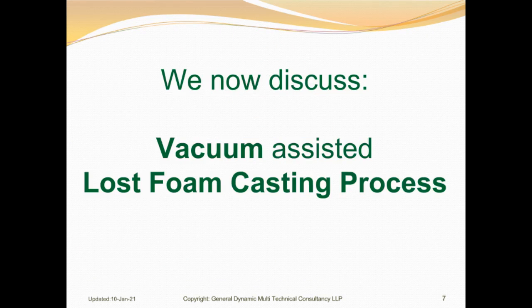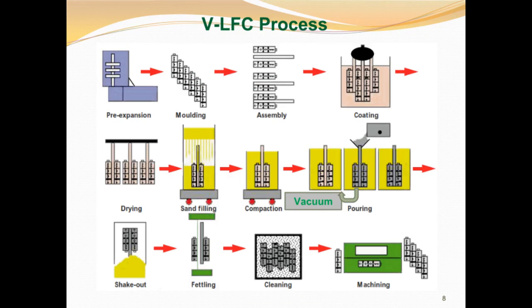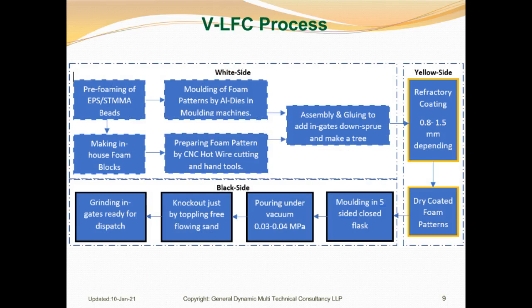Now let us discuss the vacuum assisted lost foam casting process, step-by-step. With 1 kg of EPS we can make 300 kg castings, so in fact pattern cost would be just about 50 paisa in the casting cost. That's still amazing to many of us. Firstly, we have to make foam patterns. Either EPS beads are pre-expanded and foam patterns formed by a molding machine inside an aluminum-shaped die, or we take EPS thermocol blocks and cut them to the shapes needed by hot wire CNC or a manual foam block cutting machine.